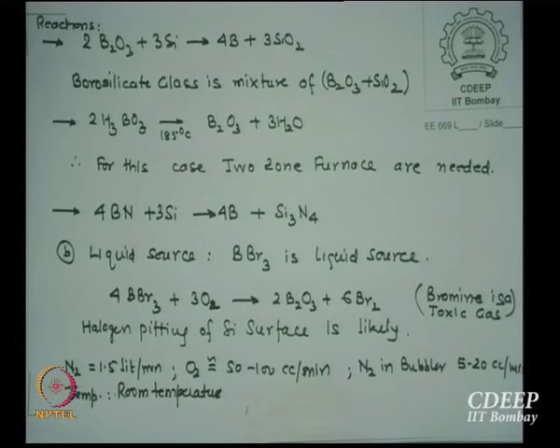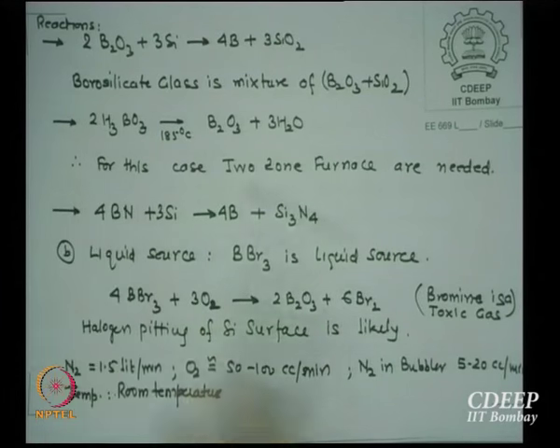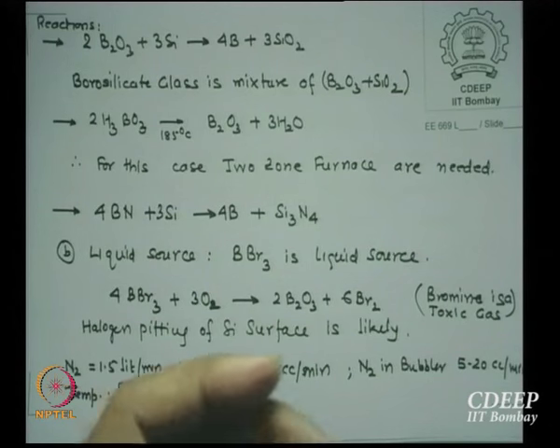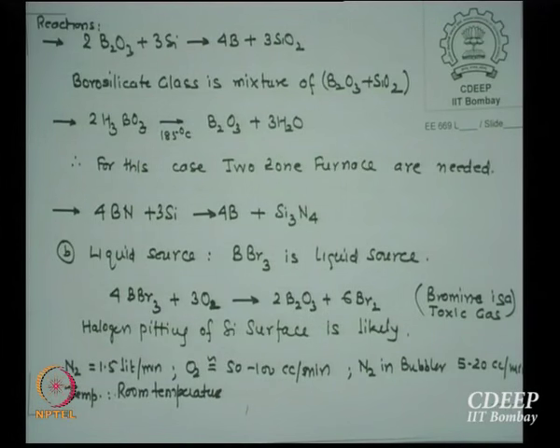There is another source: boric acid can also be reduced at 185 degrees to B2O3 plus water. The water steams out and you have a B2O3 source. For this case, in two zone furnaces, you put H3BO3 and oxidize it a little bit, and when it passes, it forms B2O3 near the surface, and that is picked up on silicon.